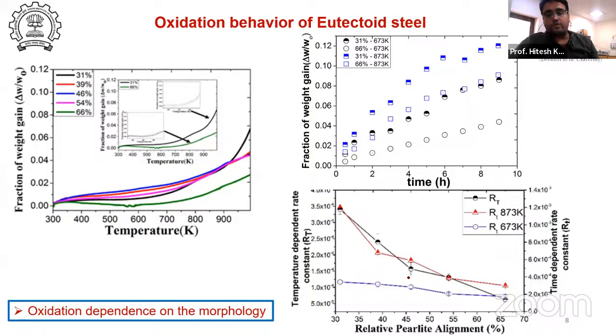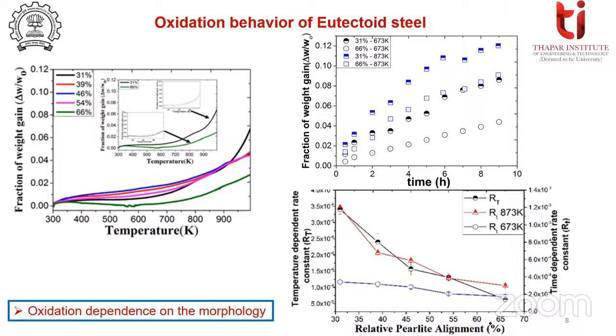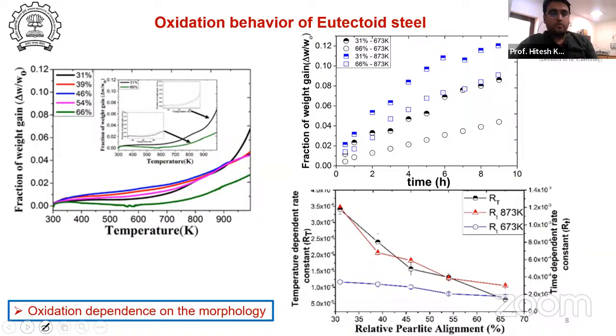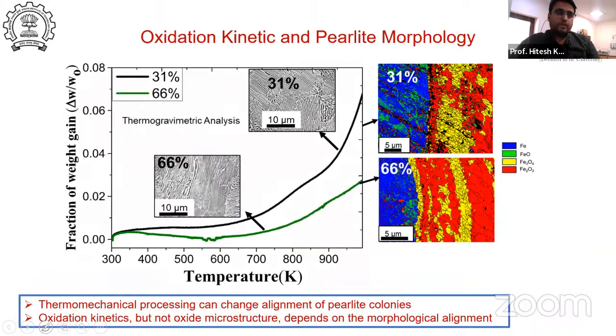We calculated the oxidation kinetics with the help of the parabolic law equation, that is y square is equal to mx plus c. So we definitely see as we are increasing the alignment, the material is getting less oxidation. Now we can comment on it. This is because of the morphology of the pearlitic colonies. Why is it happening? Is it because of the changing microstructure of the material, or are some different phases forming in the oxide scale structure?